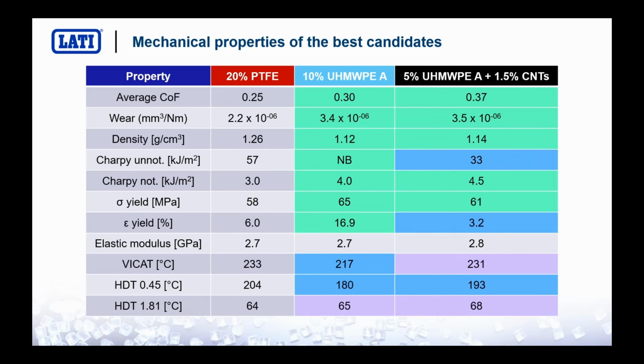We also measured all the other properties, and there are some differences with the properties of polyamide 66 plus PTFE. First of all, in the case of polyethylene plus carbon nanotubes, the material is more brittle, so we have a lower unnotched Charpy, but also a lower elongation at yield, so lower impact properties. And as already mentioned, for the compound with 10% of ultra-high molecular weight polyethylene, we face lower thermal properties, more or less 20 degrees lower for the Vicat point and also the heat deflection temperature at 0.45 megapascals. So for sure, we obtained very good results in terms of tribological properties, but we need to take care of all the properties at 360 degrees, and for sure in this case we have to face these lower thermal ones.